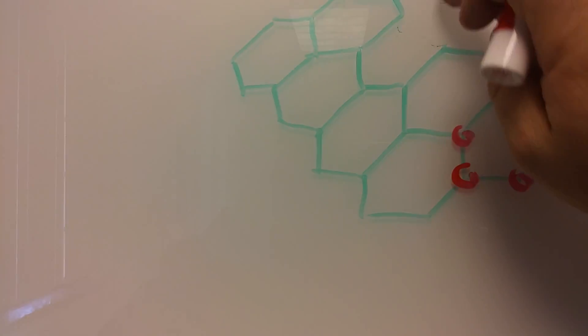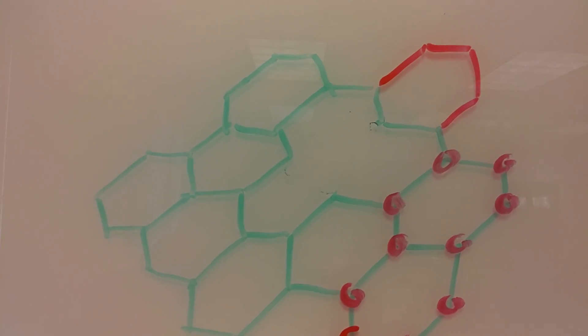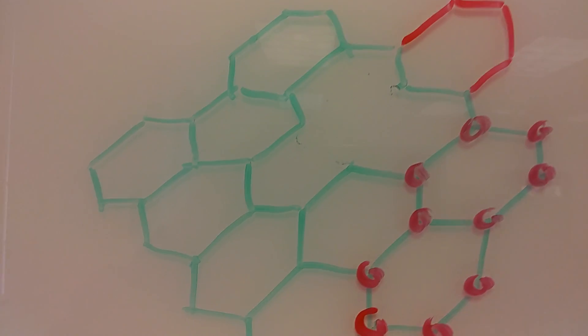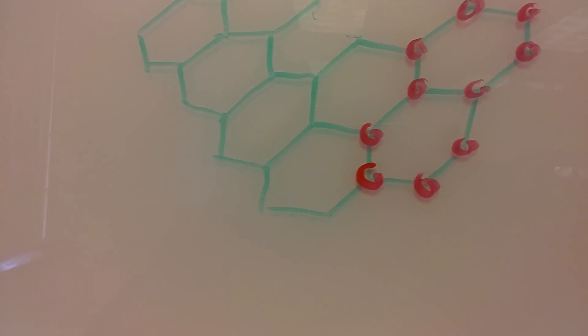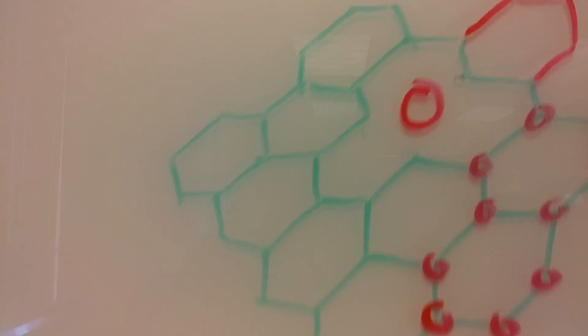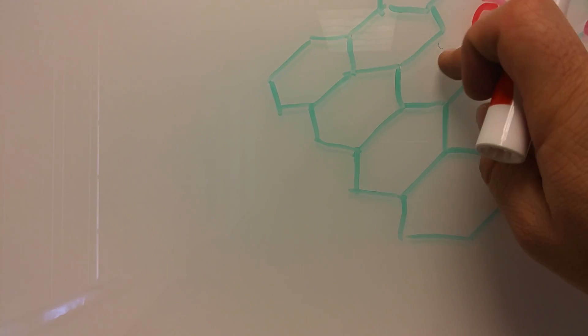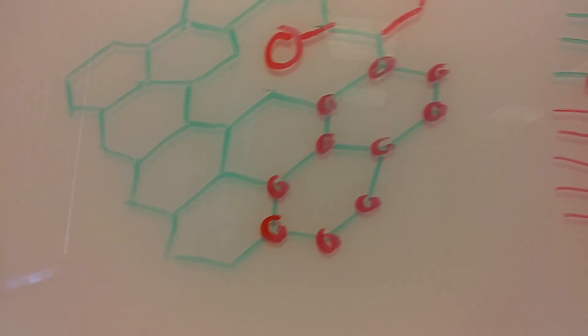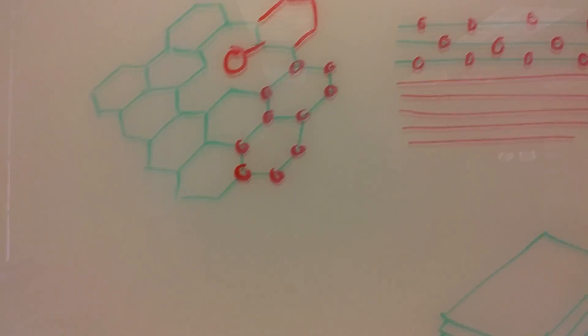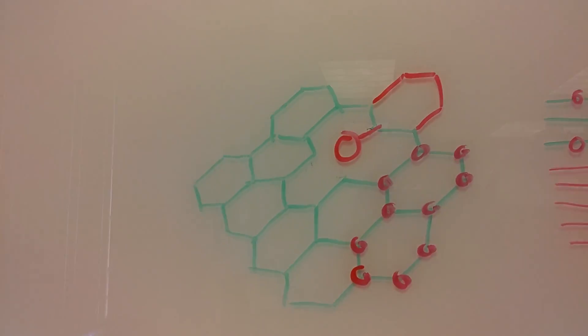You're taking away that lattice shape. So what happens there is if you have a function group in the middle of that, however it's bonded to whichever link, you still don't have that strength between here and there. That weakens it exponentially, at least that's what all the papers that I've read have said.